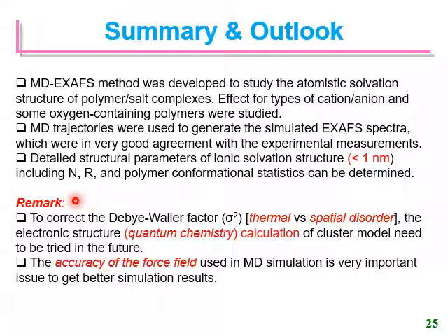However, I would like to remark that if we want to correctly calculate the Debye-Waller factors, which are composed of both thermal and spatial disorder, we need to employ quantum chemistry calculations to estimate the thermal vibration using the cluster model. We will try this in the future, I hope. And the accuracy of the force field is very important to get better simulation results.